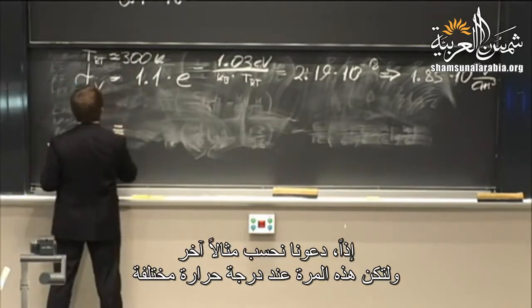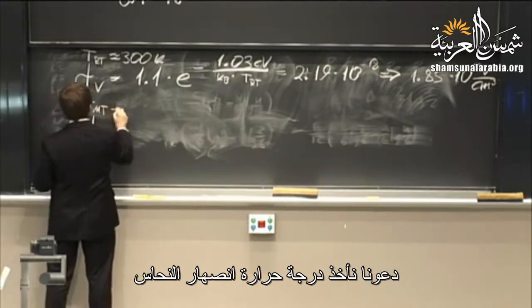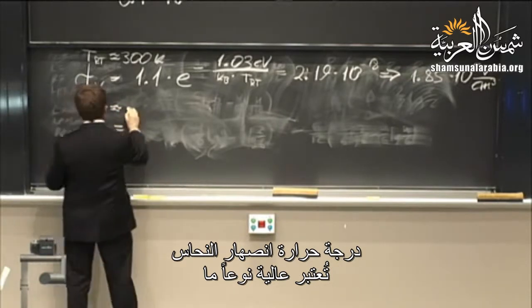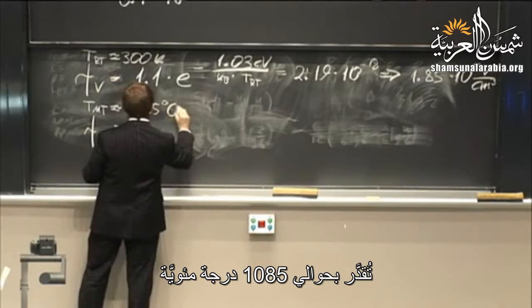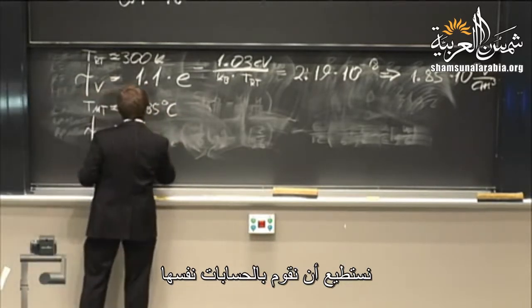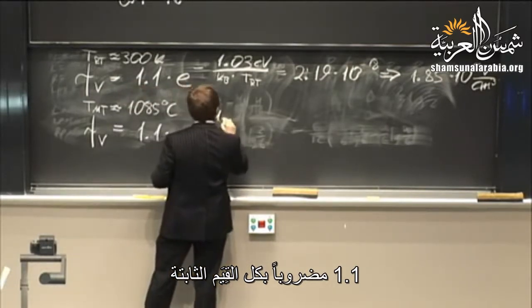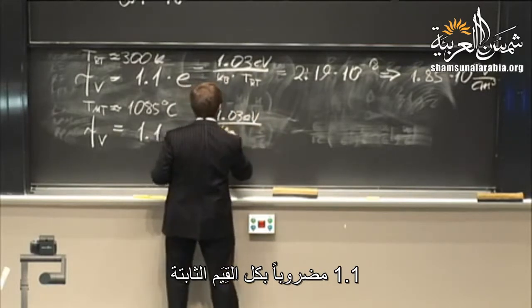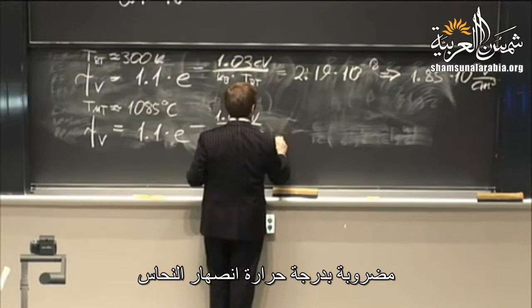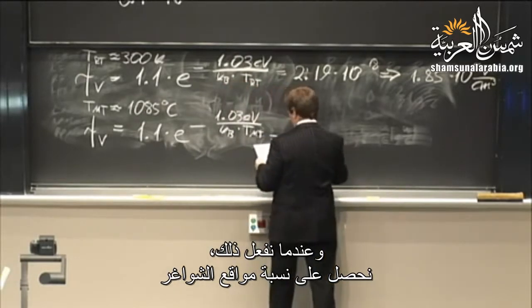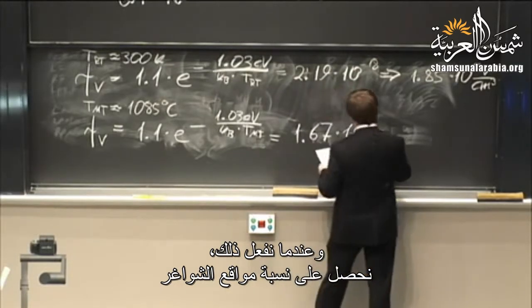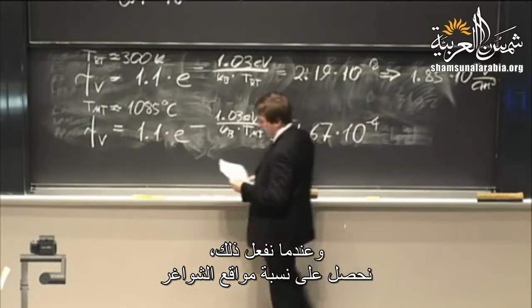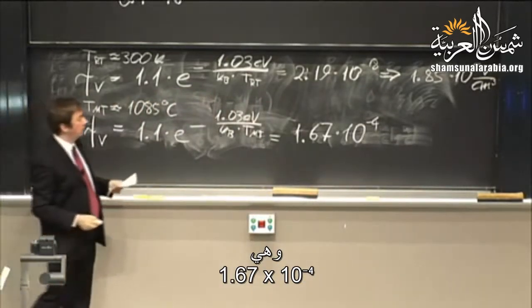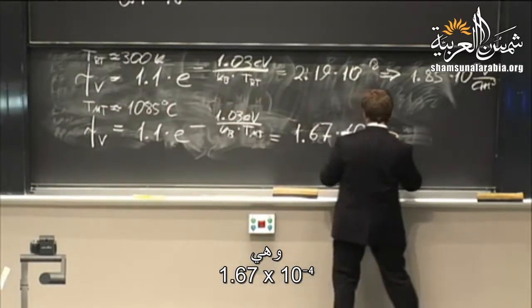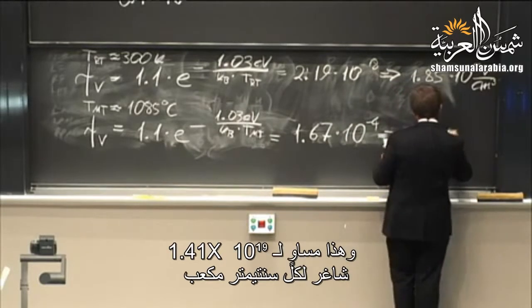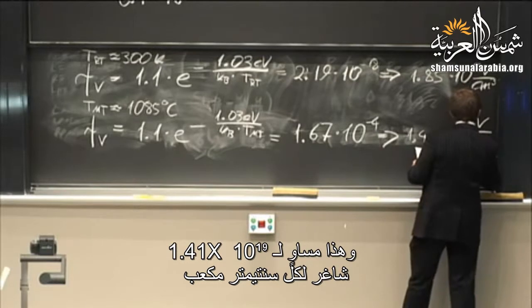So let's do another one, and this time let's pick a different temperature. Let's pick the melting temperature of copper. The melting temperature of copper is considerably higher. It's about 1085 degrees Celsius. And we can go through exactly the same calculation, 1.1 times all these quantities here times melting temperature. Okay, and when we do this, we get a vacant site fraction, which is 1.67 times 10 to the minus 4. Okay, and that corresponds to 1.41 times 10 to the 19th vacancies per centimeter cubed.